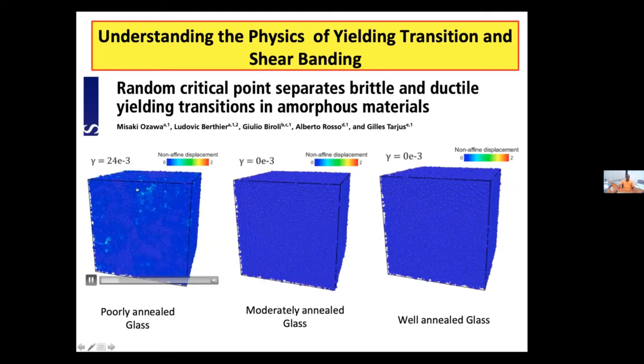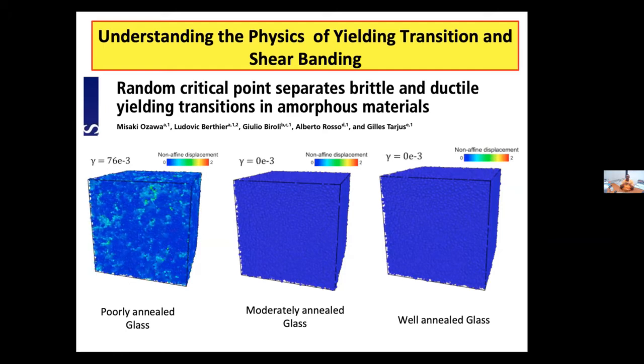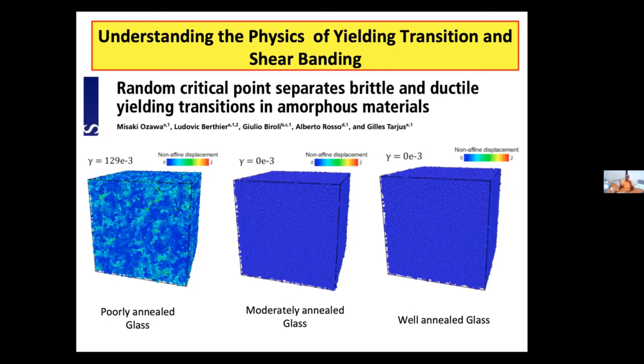For the poorly annealed glass, you see this, the colors are the places where you are basically indicating, by this parameter called non-affine displacement, the places where particles are rearranging in some sort of irreversible manner. So these are the places which we call plastically rearranged particles. So the green particles are basically plastically rearranged or deformed particles. And you see that for poorly annealed glass, plasticity seems to be happening everywhere. And so this yielding process is often quoted as ductile-like yielding.